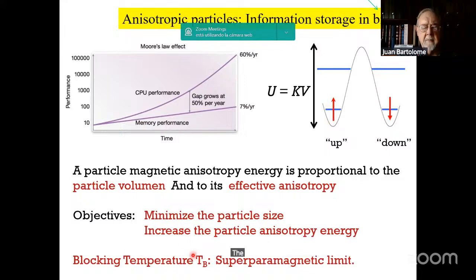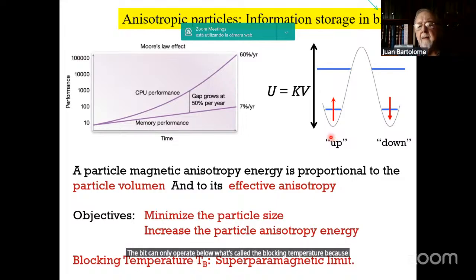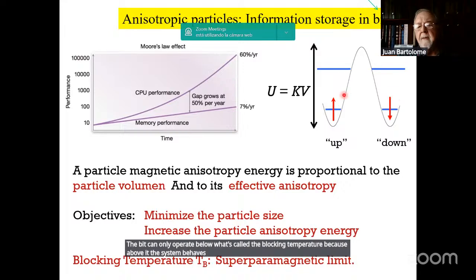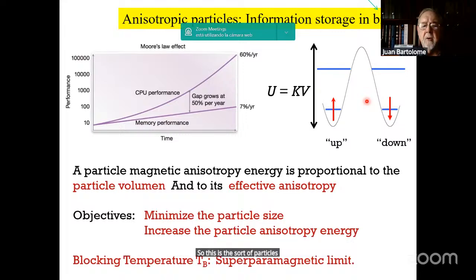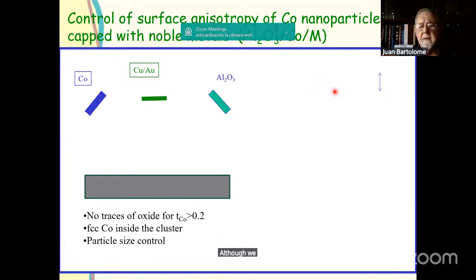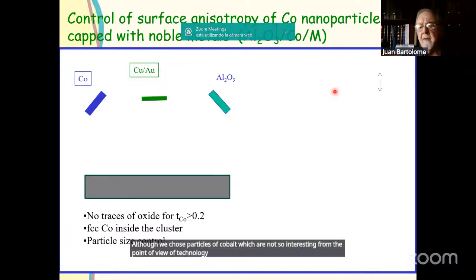The bit can only operate below what's called the blocking temperature, because above it, the system behaves paramagnetically, and so does not hold a stable magnetic orientation. So this is the sort of particles we are interested in, although we chose particles of cobalt, which are not so interesting from the point of view of technology, because their blocking temperature is quite low. But they are very interesting toy nanoparticles because they allowed us to play a number of tricks with the matrices